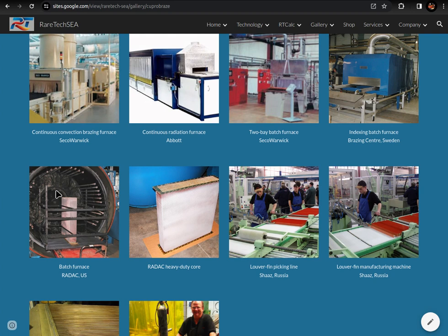He designed this furnace. There's a fan at the end to circulate, and if I remember rightly, it blew, and then across the core, and then out through the back here, through the shell. So it kept the shell cool. And then what he would do is open it up and then get cooling. I think he had a cooling jacket or something through here. It was quite a sophisticated furnace. It worked quite well. So it's a very different design, with different ideas to these kind of furnaces.